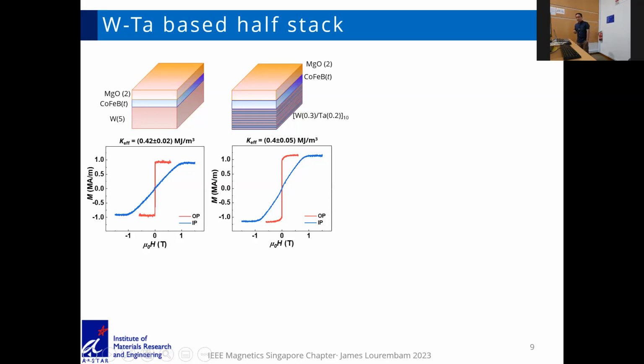So this is what we call the half stack. We typically develop the half stack first before developing the full magnetic tunnel junction. In this case, I've shown an example comparison of just tungsten as well as the tungsten-tantalum multilayer. Here in Singapore, we use sub-monolayer deposition to get this tungsten-tantalum multilayer.